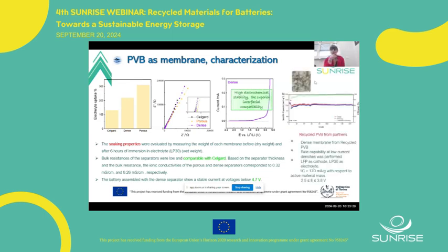We also achieved recycled PVB from our partner Loureiro, and tried to make the membrane and all the characterization again with the recycled one. We tested it in a half cell for lithium-ion batteries with LFP as cathode and lithium as anode, and as you can see, we could achieve quite promising performance with the recycled membrane.